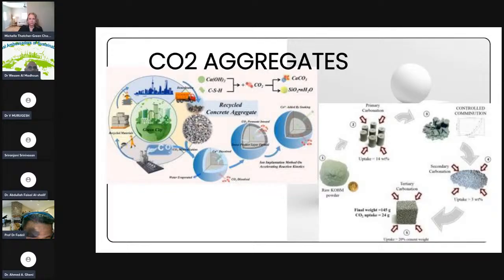This slide shows how we are producing CO2, how we are producing aggregates from the CO2. Nowadays people in the construction industry are talking about RCA, recycled concrete aggregate. So actually this is one of the methods to reduce the impact. Instead of using natural aggregate, we might also use recycled concrete aggregate. But somehow the recycled concrete aggregate has problems due to poor quality aggregates and low strength of aggregates.